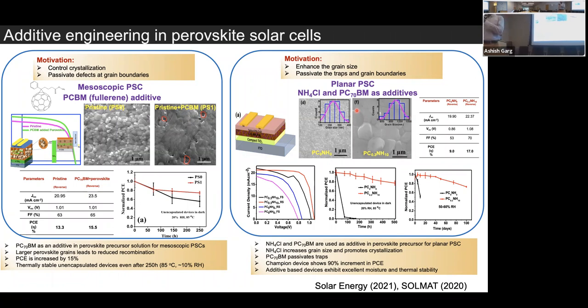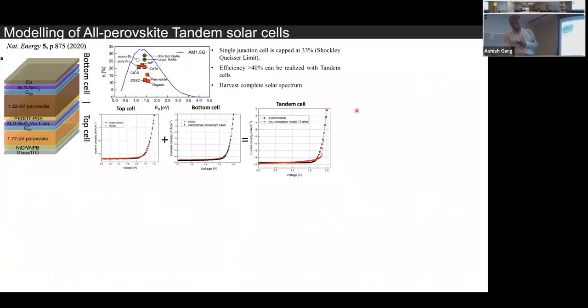And this is, by the way, on methyl ammonium lead iodide. There is no other composition modification. So these are good efficiencies that we have obtained, especially the lifetime. That higher lifetime can be achieved by reducing the defects in the active layer, which could be either through modification of the electron transport layer, or by adding additives, or by doing other kind of microstructural engineering.